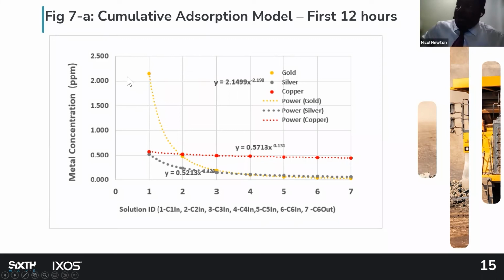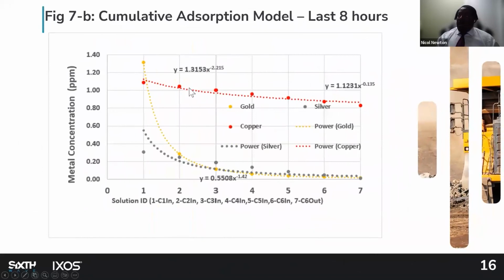And it looked very good because the gold was showing very low concentration in the last tank 6, which buttressed what we found in the lab. The copper, on the other hand, was virtually not being removed from the circuit, which again buttressed what we had in the lab. And the silver was also being pulled out of the circuit, which buttressed what we had in the lab. And we ran the last 8 hours.